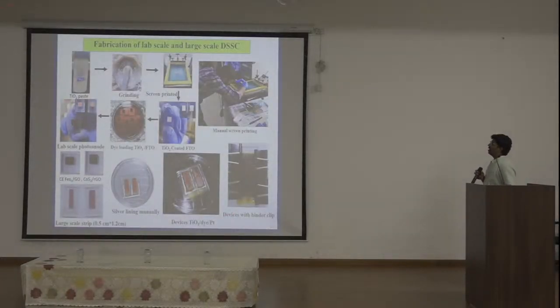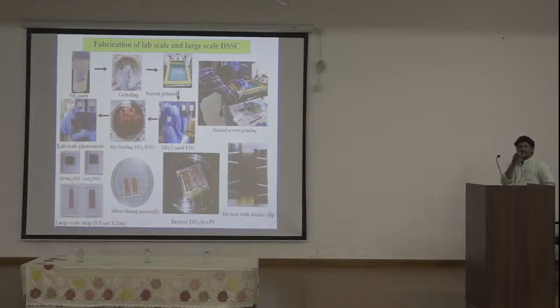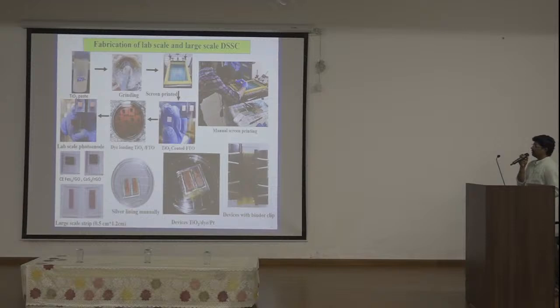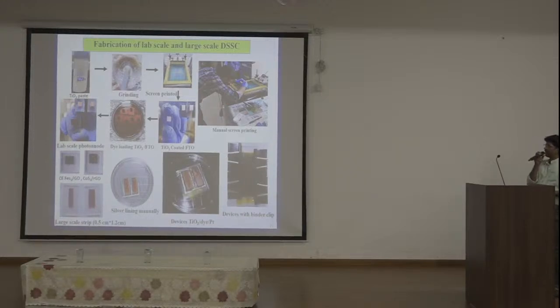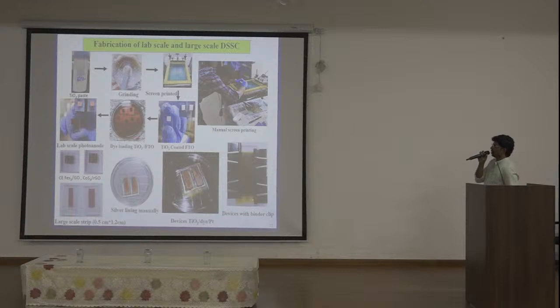This is how we have fabricated the solar cell at lab scale as well as the large scale submodule. We make the TiO2 paste, grind it, and screen print it. Here we have optimized the TiO2 photoanode with the screen printing method, 14 strokes over the layer we have coated. It gives the optimum thickness of 14 micrometers. And after dye absorption, more dye molecules are absorbed on the surface of the TiO2.